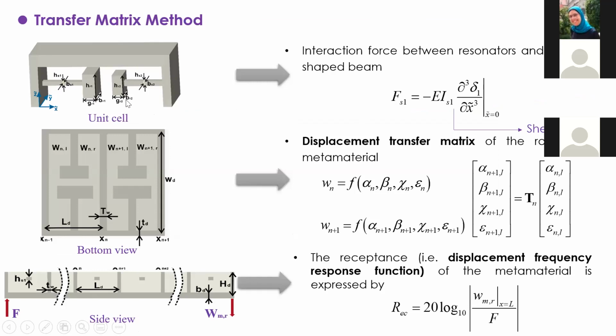First, we calculated the interaction force between the resonators and the host beam, like this, based on the shear force calculation formula. And then we related the displacements at different unit cells based on the transfer matrix. Then we assume a force excites the beam at one end, and we can calculate the displacement at the other end. With this excitation force and the displacement, we can calculate the receptance function, which is the displacement frequency response function of this material beam, like this.